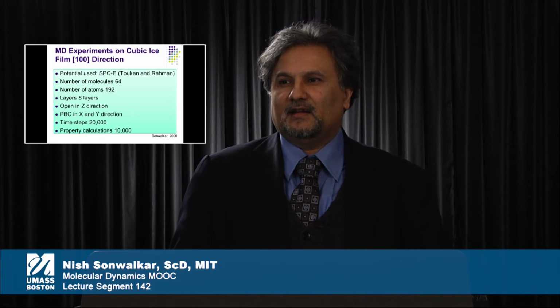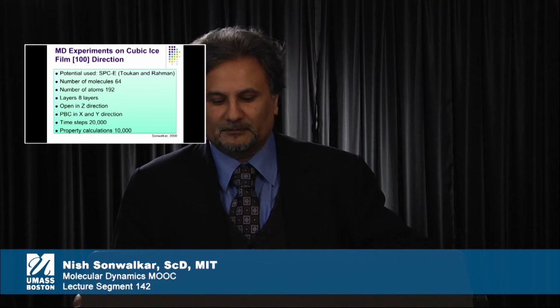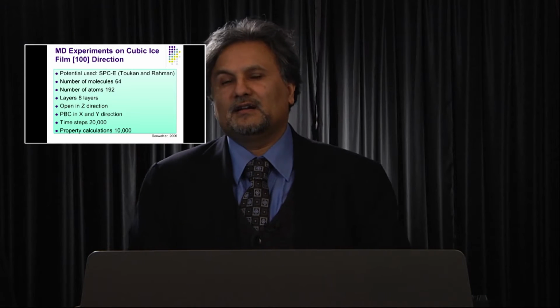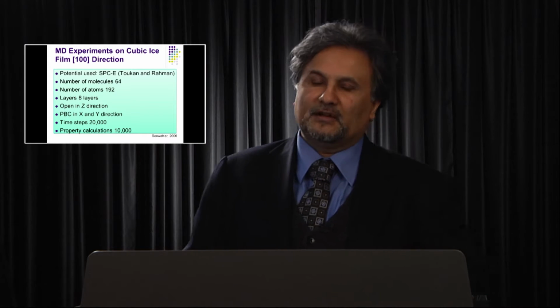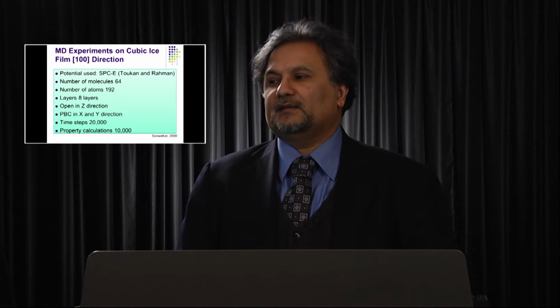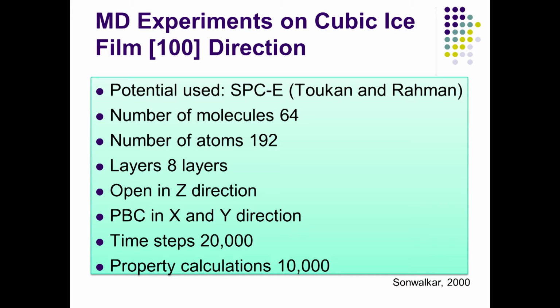Welcome back. Now we are going to look at an experiment that I conducted a long time back. As in some of my earlier experiments with molecular dynamics simulation, I used the SPC/E potential, the simple point charge potential that we discussed earlier by Toukan and Rahman, and I took a number of molecules as 64, created 8 layers of them, and then opened in the z direction.